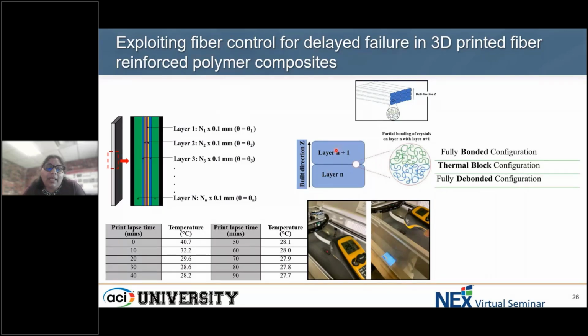What we noticed from experiments is that when we immediately print layer N, the temperature on that layer N is about 40 degrees. After we've waited 20 minutes, it's about 29.6 degrees. After about 40 minutes, it reduces to 28.2 degrees. And so forth, until at 90 minutes of print lapse time, it's about 27.7 degrees at the layer interface.